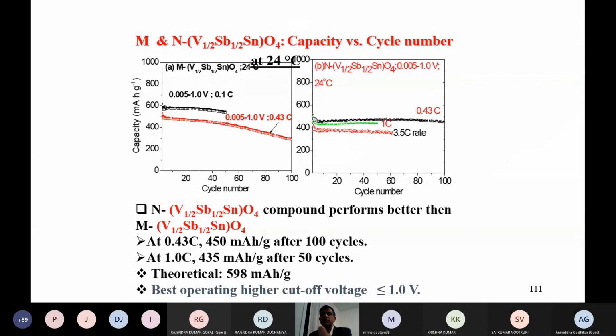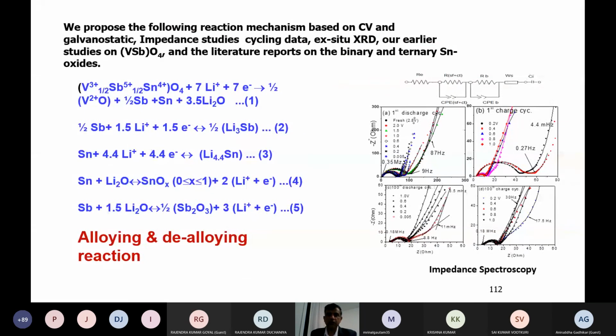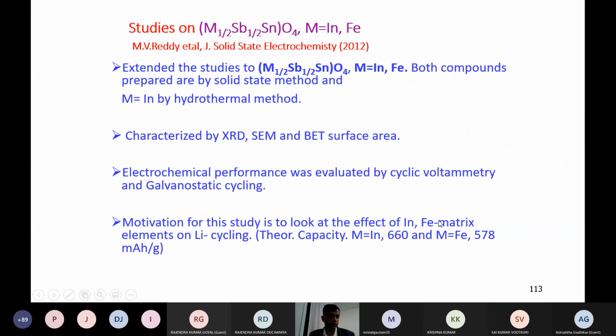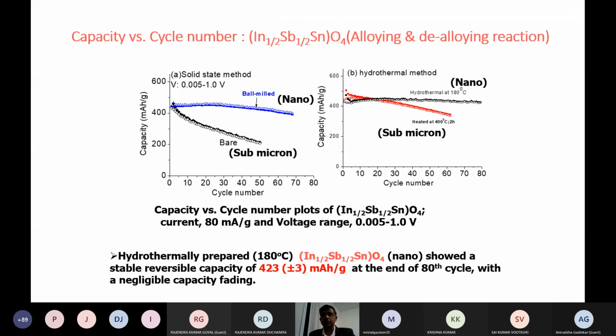If you go from micron size to nano size, micron size seems to show a little more capacity fading when compared to the nano size material. We proposed different ideas about the real mechanism, and we checked with impedance. It gives information on how the resistance of the cell changes with long-term cycling. I think that is the way it gives information about the sample. And another way, I told you about alloys, we can use the same concept. You can use iron- and indium-containing materials, and we can try to prepare the samples using this approach. And it is one example.